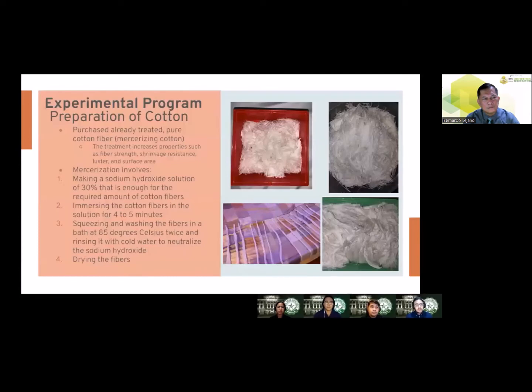For the preparation of cotton, the cotton used for the experiment was already treated using mercerization, which increases the fiber's strength, shrinkage resistance, luster, and surface area. Mercerization involves immersing the cotton fibers in a sodium hydroxide solution of 30%.